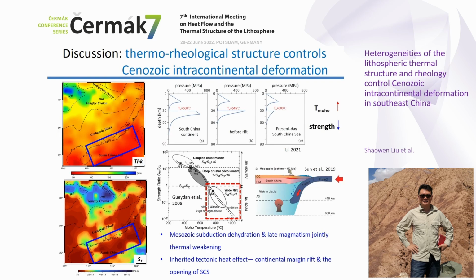We also discuss the control of the thermorheological structure on the Cenozoic intracontinental deformation. The numerical simulations show that the temperature increases and the strength decreases during the rifting of the continental margin. This is consistent with the thermal weakening of the Mesozoic subduction dehydration and later magmatism. According to the prediction of the numerical model, the present temperature and strength ratio pattern will lead to a wide rift. So, we propose that the inherited tectonic thermal effect in southeast China controls the continental margin rift and the subsequent opening of the South China Sea.